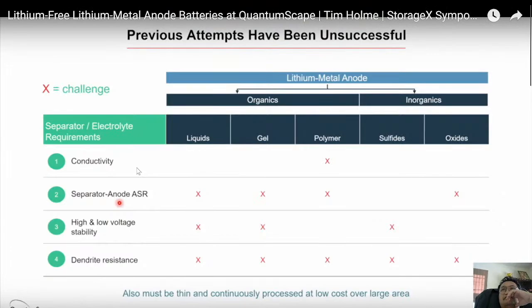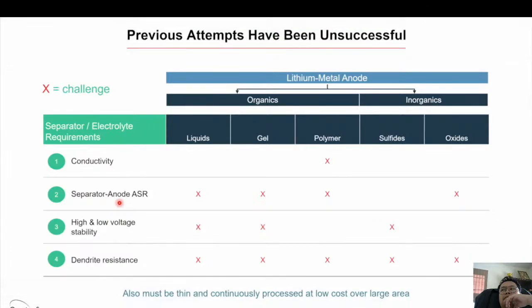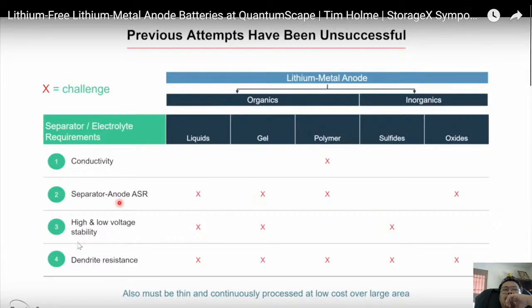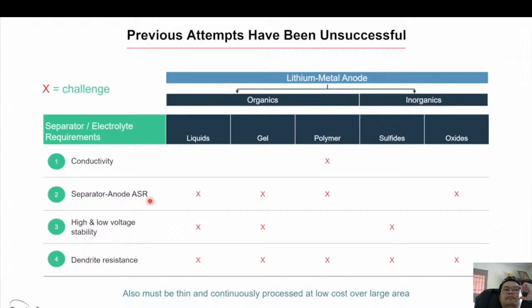One of the things that's a little bit subtle and sometimes underappreciated is that there can be as much resistance at just the interface between the lithium metal anode and the separator as there is throughout the entire bulk of the separator. So to be able to have a high power battery and enable fast charge, you need to have a low interfacial resistance. ASR is an area specific resistance.